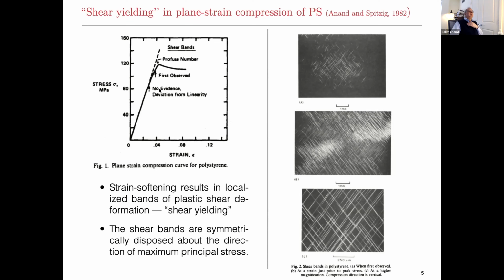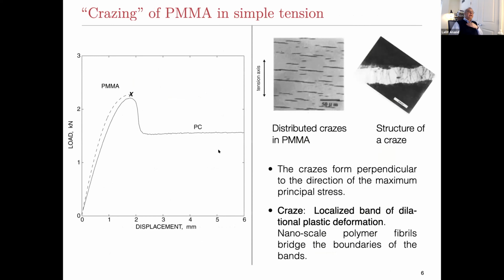So before the peak, you get some shear bands, and then near the peak, you get a whole bunch of shear bands. And these shear bands, of course, this is in compression, the vertical direction, they're symmetrically disposed to the maximum principal stress direction. Okay, so that's in compression. The response in tension is quite different. There is shear yielding prior to the peak, but PMMA will actually fail very close to the peak.